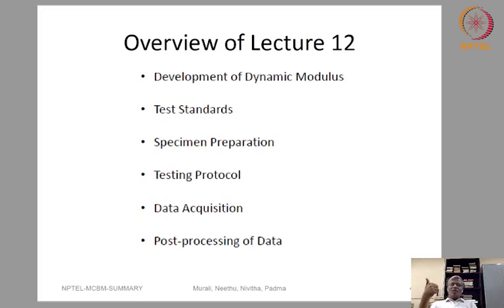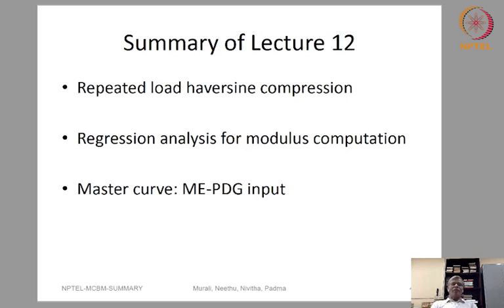There are a few basic assumptions that are made in this dynamic modulus test. One is linearity. It is assumed that the response of the material can be taken as linear if the strain levels are between 75 to 125 microstrain. Number two, in the post-processing method, you are not fitting any linear viscoelastic model; rather, a regression approach is used, and based on the coefficients of the regression equation, one computes the dynamic modulus and phase angle. So, this is the summary related to this particular lecture.